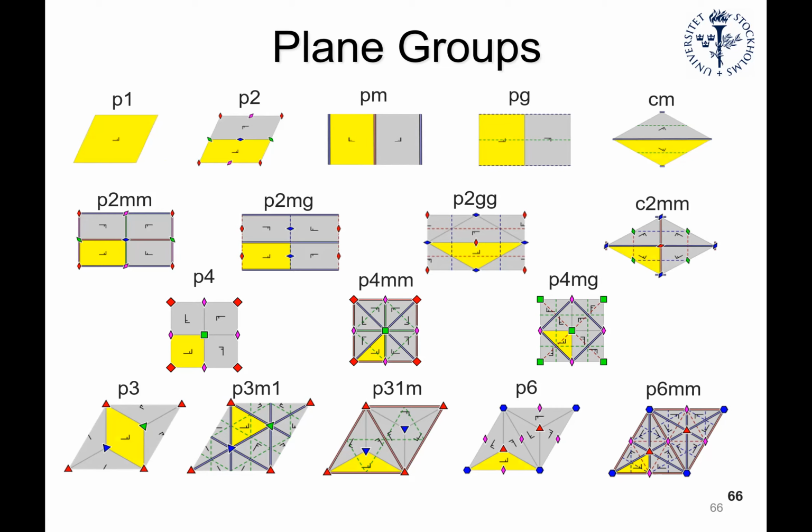So the difference between P3M1 and P31M, since the names are quite similar. They both are primitive lattices, they both have threefold rotational symmetry, and they both have mirror planes. But you can see that the relative positions of the mirror planes are different. For example, in P31M, there's a mirror plane that goes along this short diagonal here, and also along the edges of the unit cell.